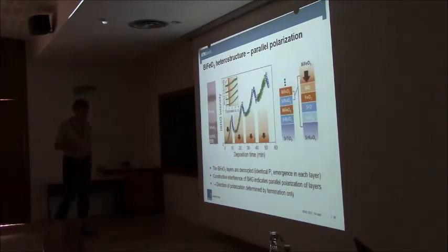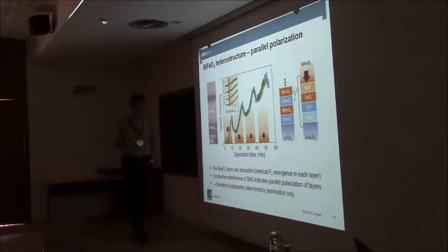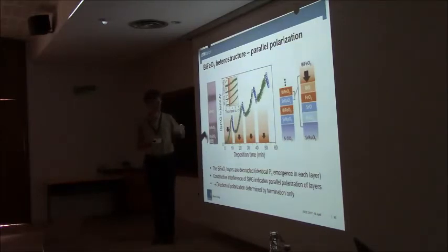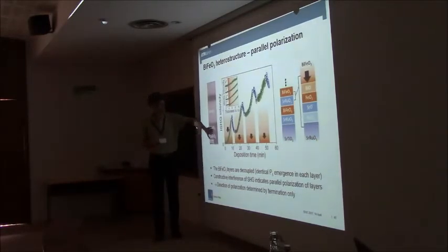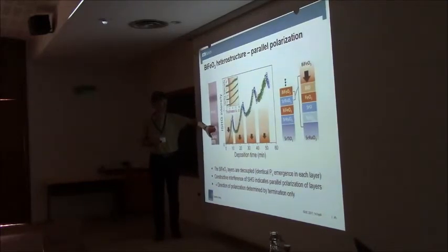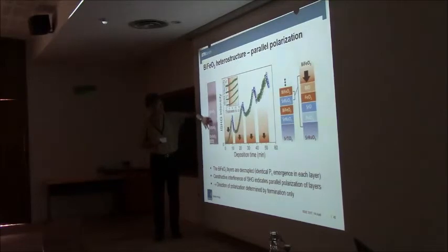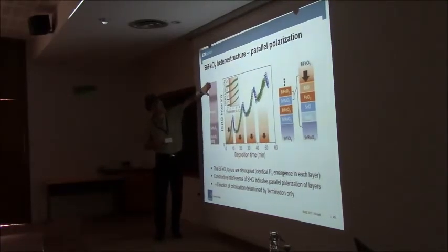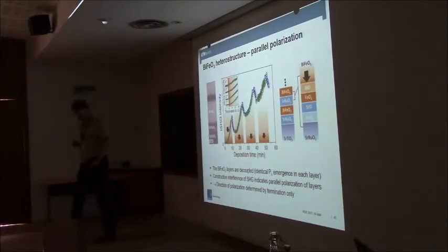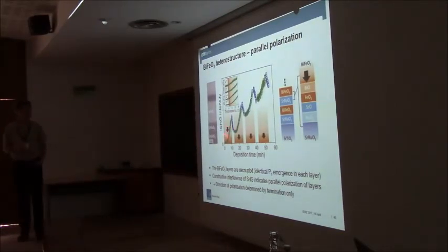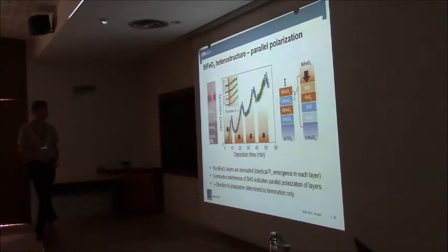Okay, so here is this other idea. He then said, let's try to go uniformly polarized, layer by layer, on top. So always substrate, a metallic layer for screening, then the ferroelectric layer, another screening layer, ferroelectric layer, another screening layer, and so forth. And then you can see, yes, all the bismuth ferrite layers grow uniformly down polarized. They like to do this, and the different layers are not coupled. In all layers, first, second, third, fourth, always after something like 4 unit cells, your ferroelectricity emerges. The layers are really decoupled, because of the metallic interlayer.